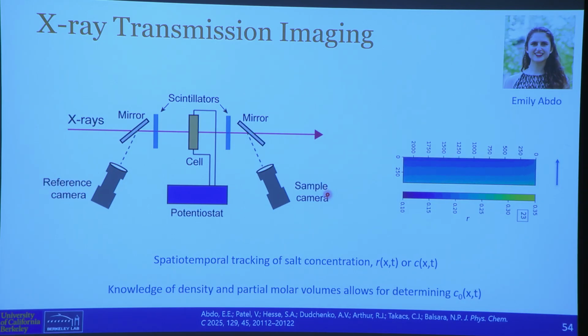The last thing I want to tell you about is this crazy experiment of Emily Abdo and Chris Takis, where you take a lithium-lithium symmetric cell and take X-ray images, and you do the normalization in such a way that when you take a picture, you actually get the salt concentration. It's literally dark light, and then you quantify it. So what you're seeing here is a movie of salt concentration as a function of time.